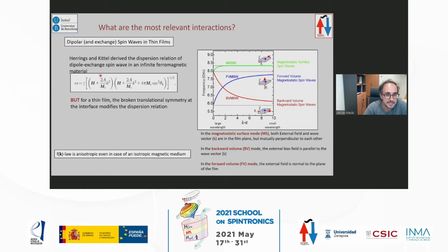Actually, Kittel, we also saw already the Kittel formula. Kittel derived the dispersion relation for dipole-exchange spin waves in an infinite ferromagnetic material. This is not a thin film with borders. This is infinite, but you can see that if you look at k equals 0, we get the gamma H that we knew. And also there's something interesting, which is that the propagation in the direction of the applied field is different than the propagation perpendicular to the applied field.